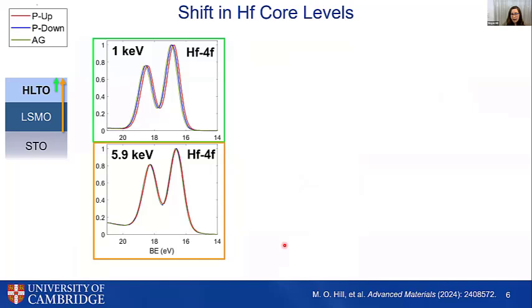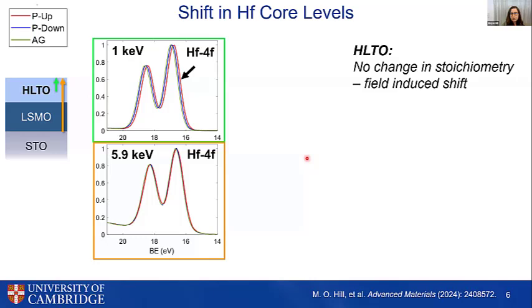If we look briefly then at the hafnia core levels, we can see for 1 keV, we get a shift in HLTO in the hafnia peak. But this shift isn't a change in the peak shape, it's just a pure shift, which suggests that there's no change here in our stoichiometry, but instead some kind of field-induced shift in the P up condition. And then we see this mostly in the top of our film. We don't see it again once we're probing deeper at 5.9 keV.